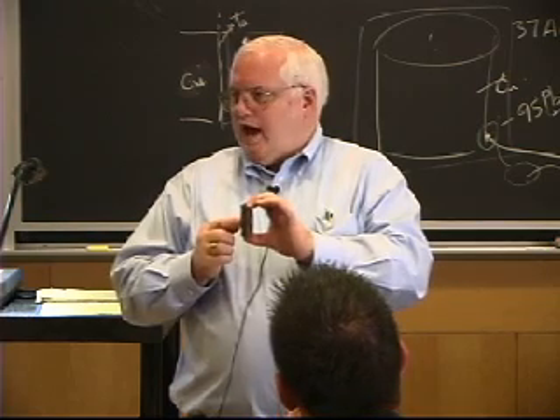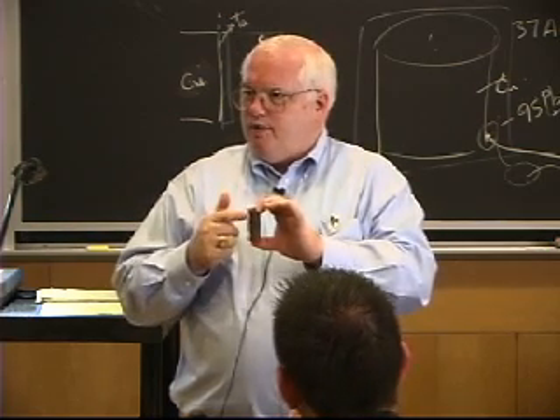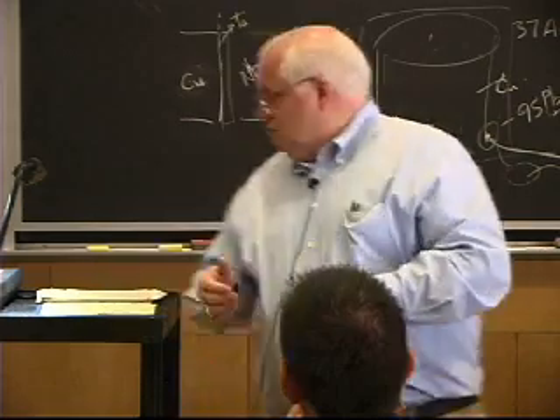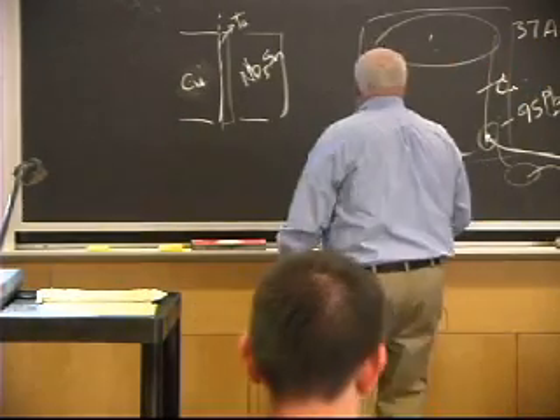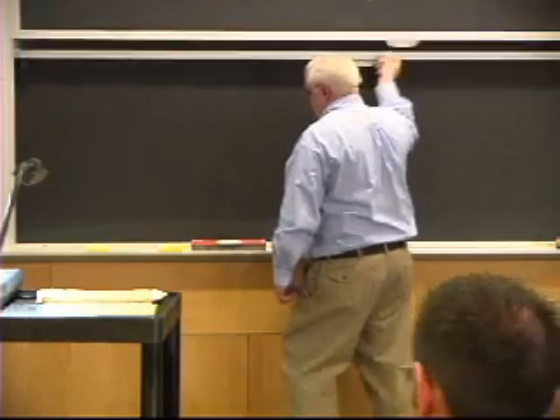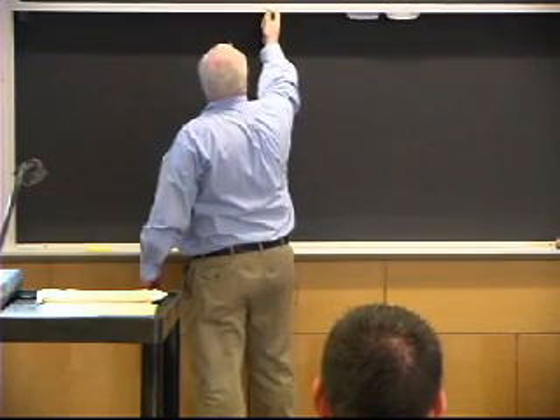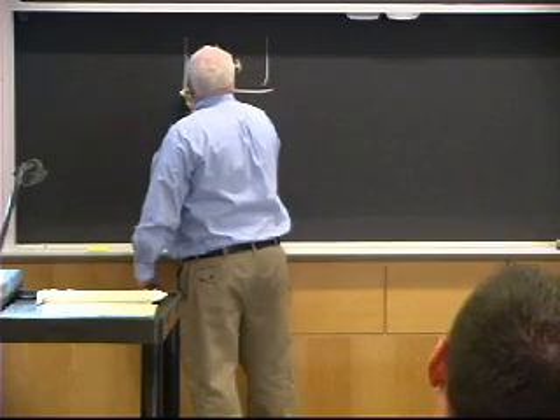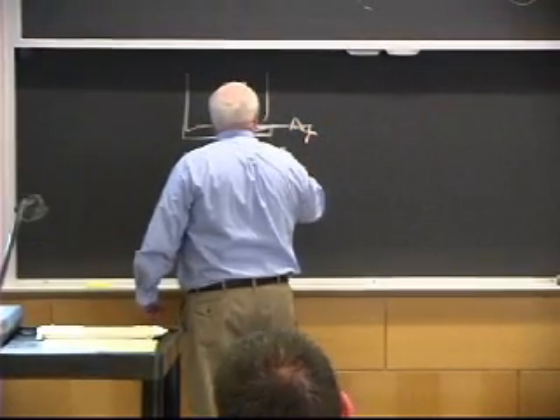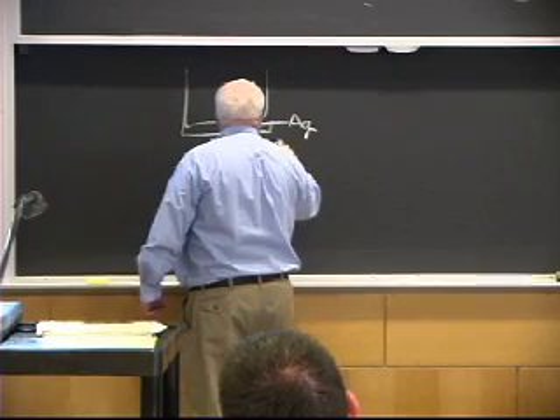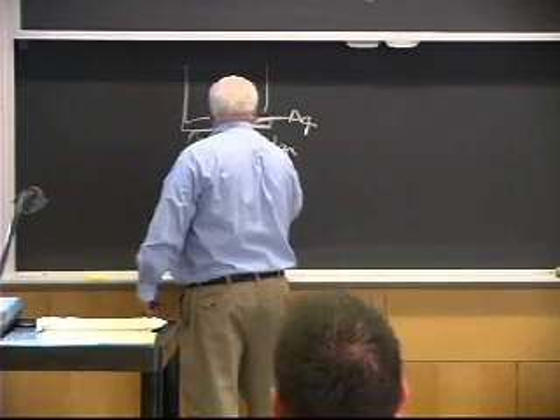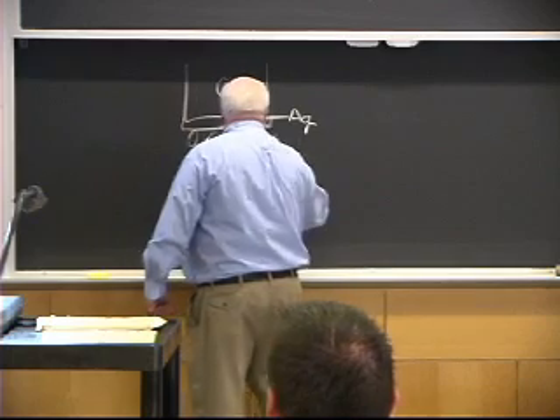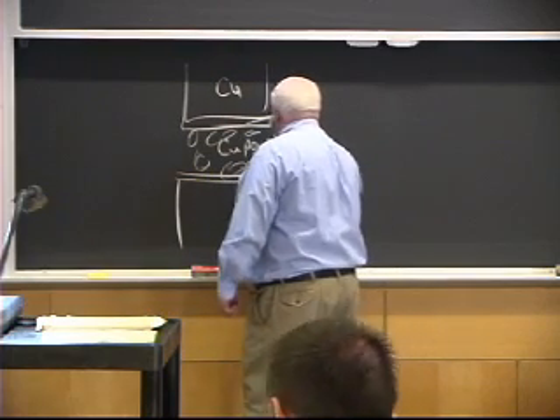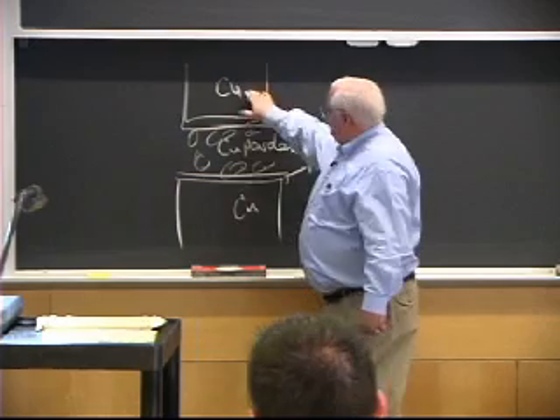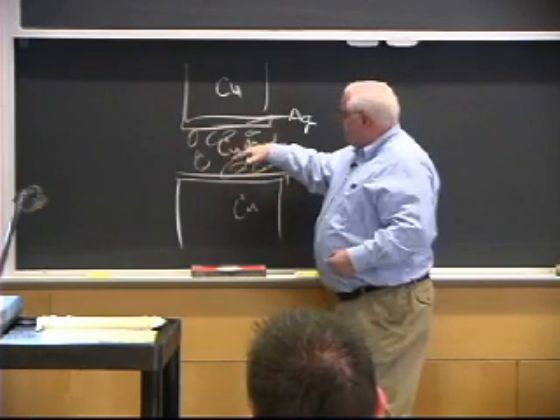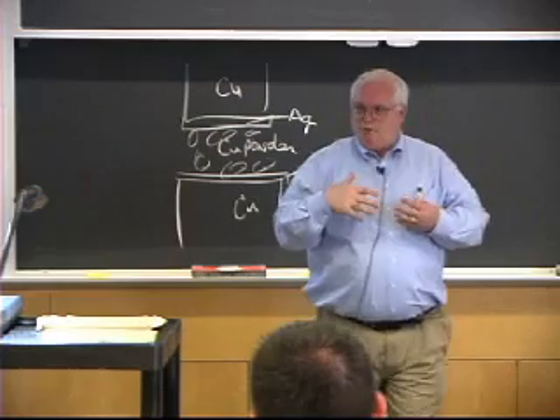Well, we wanted something that would fill a gap, and so we started putting copper powders in with silver powders and melting the two. You need to fill a gap, and what we had was some copper. We put a piece of silver foil in there, we'd put some copper powder in here, and then we would put another silver foil, and then copper. So you have the two pieces of copper you want to bond. You put some copper powder in here to fill the gap, and you put the silver in. We figured we just infiltrate the copper powder with the silver.